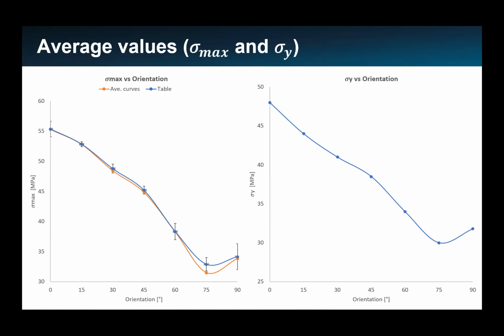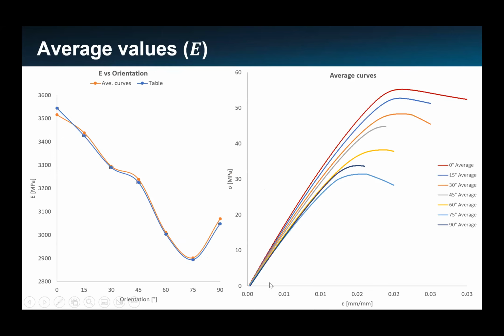So this is a curve that relates the maximum strength with respect to the orientation, and here we are seeing the yield stress versus orientation, and here the Young's modulus versus orientation. In this figure we have the average curve of each orientation, and you can clearly see that the strength reduces as the orientation changes.